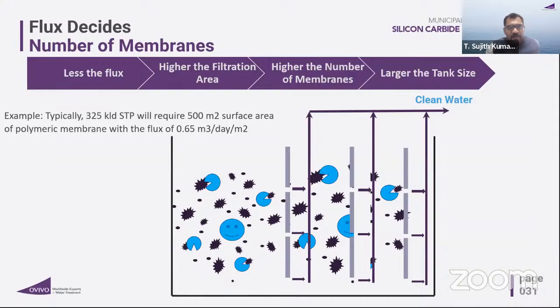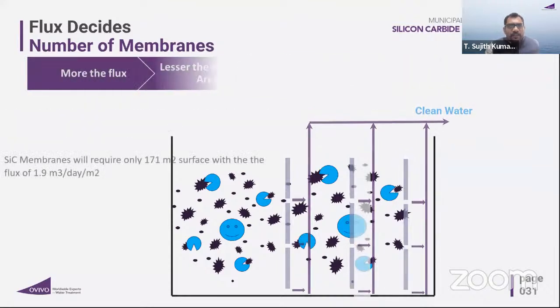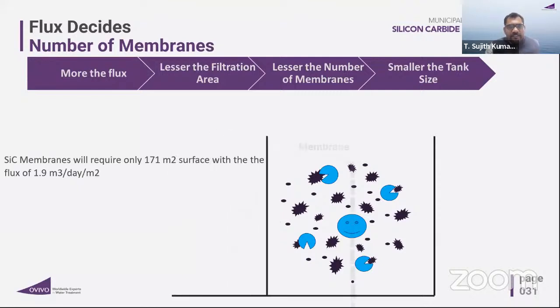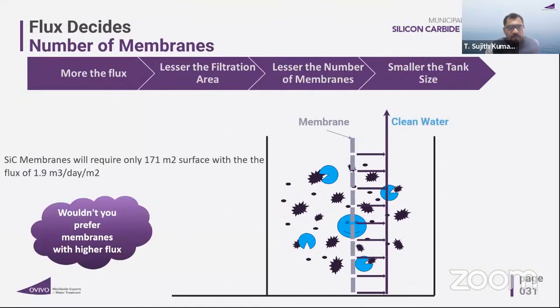It's a typical example what we have shown for a 325 KLD of STP. You need a polymeric membrane area of 500 meter square, with the flux of 0.65 meter cube per day per meter square. This is the typical polymeric design. Whereas if you go with SiC membranes, you need just 30%, 40% of it, 171 meter square area, that's it. Your footprint also would be very less because we take the flux 3 times. In polymeric, you can take only 0.65 meter cube per day per meter square. Here we can go up to 1.9 meter cube per day per meter square.